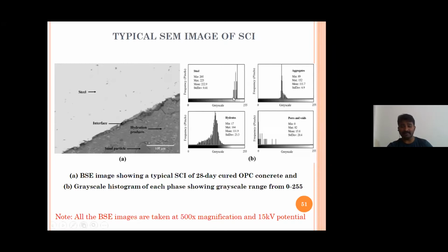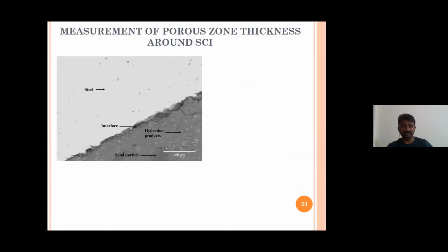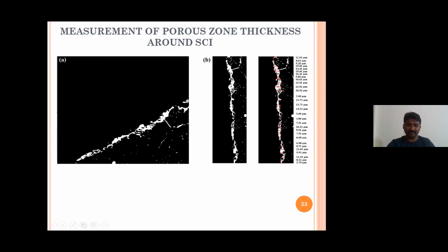So now what is happening here? In a few portions of the hydration products, the minimum grayscale value is 17. The pores vary up to 82. There is an overlap of hydration products and porous zone. To bridge that gap, we have used the grayscale thresholding method. Once I apply a grayscale thresholding value, which we got from one of the other papers, for this purpose I've used the image analysis tool ImageJ, which is a free image analysis tool. If I threshold this image with a gray value of 42, I'll see an image of this kind.